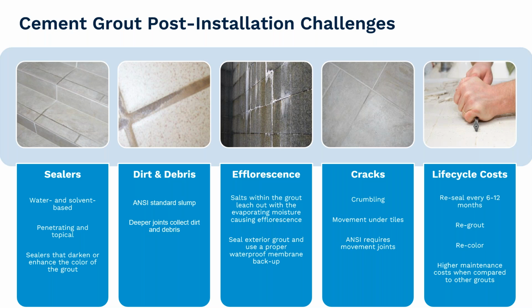There is dirt and debris. As I said before, just common on the job with the air, you may get some dirt and debris that is in the tile, as well as deeper joints do tend to collect some dirt and debris. So when you're going through and you're cleaning up as you go, you want to make sure you're getting that debris out. Efflorescence, so the salts within the grout do come out as they evaporate in the moisture. Seal the exterior grout using a proper waterproof membrane. That can also help to mitigate the efflorescence that you will see.